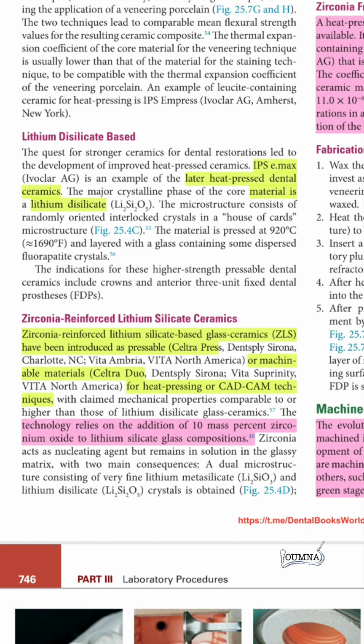The leucite reinforced glass ceramic was named IPS Empress, but it is only used for the anterior part of the mouth because it is not so mechanically applicable in the posterior part of the mouth. So the addition of lithium disilicate to the ceramic base has increased the strength, and we got the material that is called Empress 2. When the percentage of the lithium disilicate increased to 70% of the glass matrix, it is now called the IPS e.max ceramic material, and now it can be used for the anterior crowns, posterior crowns, inlays, and veneers.